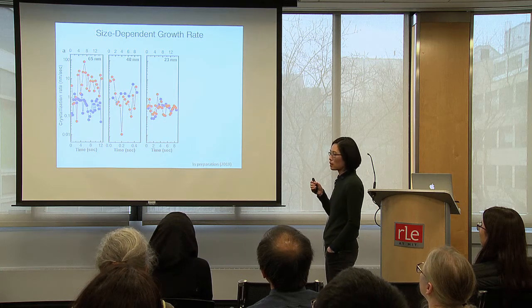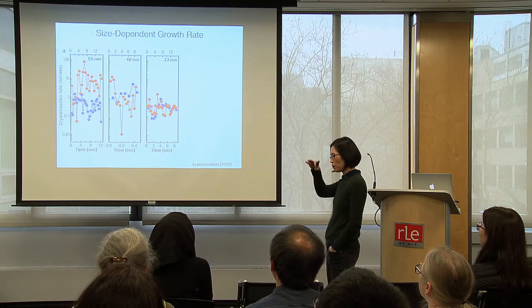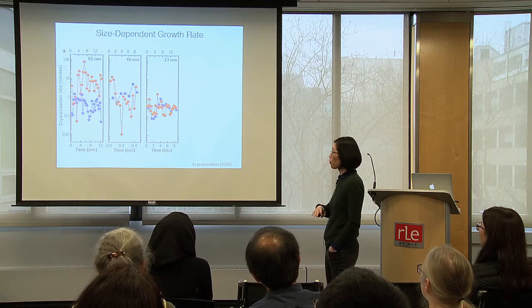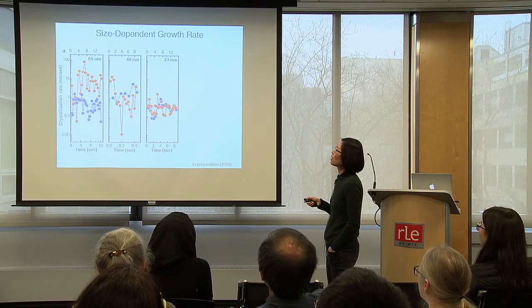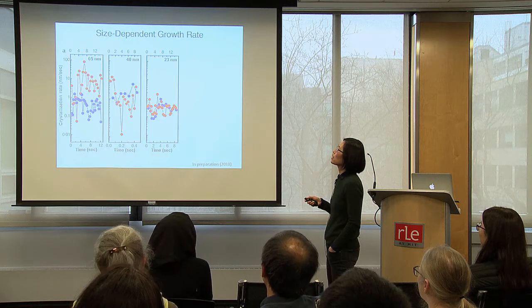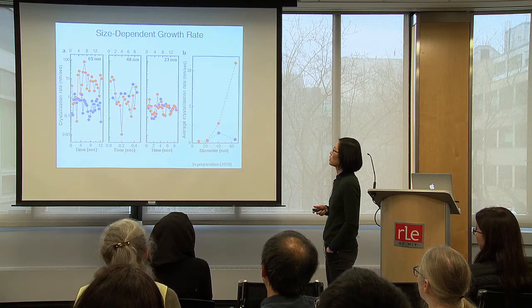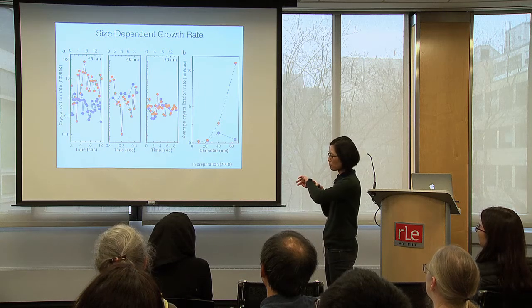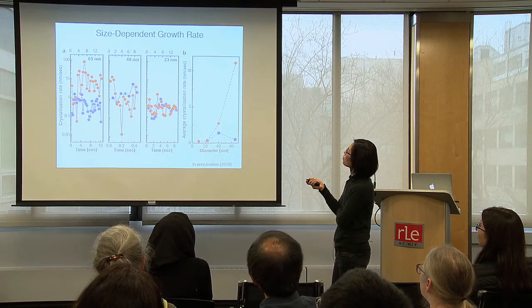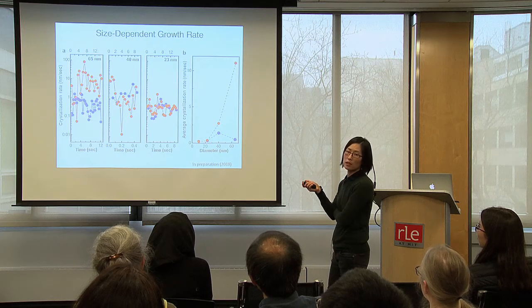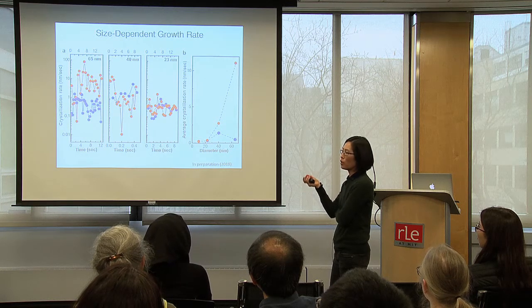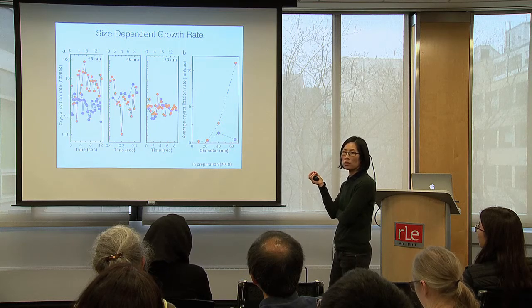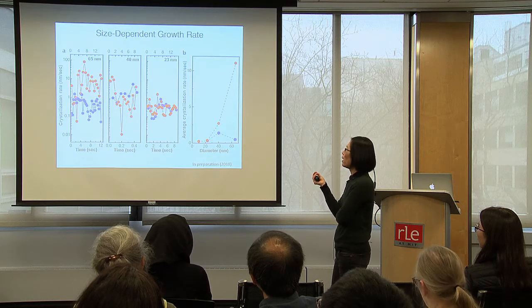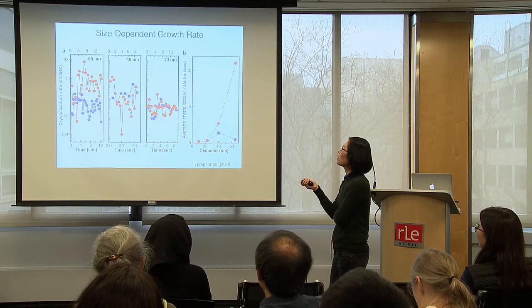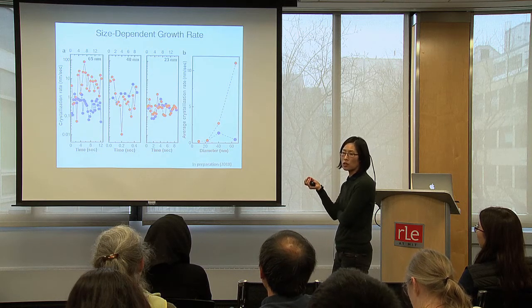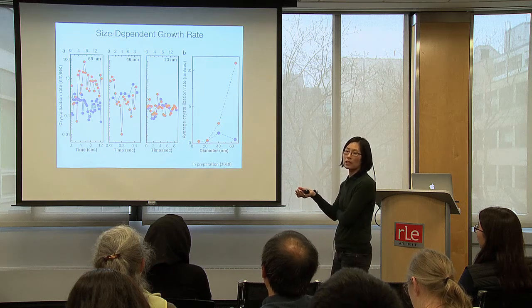And the blue means I'm doing crystallization from the liquid side. The red is coming from the glass. So another thing you see is that when you're crystallizing it from the glass, your growth rate is much higher. Okay, so right now we're in the middle of analyzing these data, but it certainly shows you that classical nucleation theories fail here. And what we believe is that there are substructures in the glass that are enhancing crystallization.